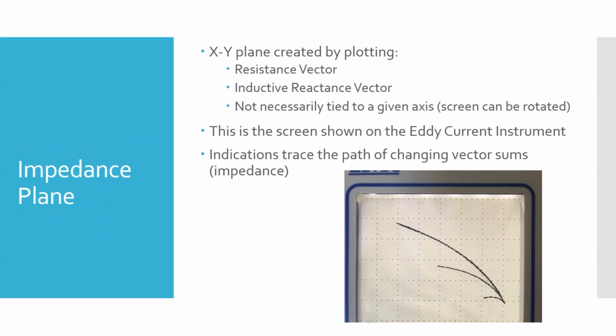And we can adjust how zoomed in or how zoomed out we are, because different materials and different flaws are going to have bigger or smaller indications. And so we can make adjustments to compensate for how sensitive we need to make our probe. We can adjust how much power we're sending in the probe, which will play a part in how strong those eddy currents are and how strong the induced magnetic field is. We can adjust the sensitivity of the pickup coil, whether it's the same coil or a second coil. We can adjust what's called the gain on that.